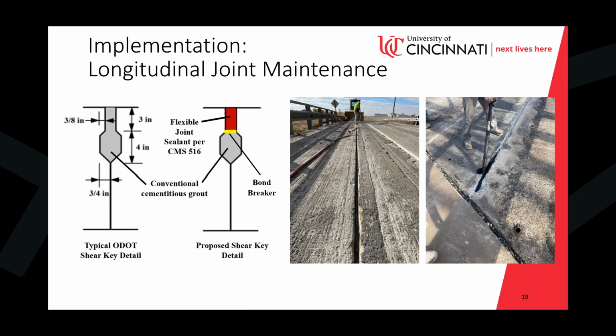The detail on the far left is showing the typical ODOT shear key detail. So typically you would grout it with the cementitious grout at the geometry and the depths that are shown in the image to the left. What we wanted to do in this maintenance, acknowledging the fact that there is a lot of cracking that happens and a lot of thermal stresses that are induced, particularly at the top, is to install a flexible joint sealant at the top so that it can accommodate differential movements that might happen and the stresses that could be present there. And so that is what we observed and had done again on 2 bridges as part of this maintenance procedure.